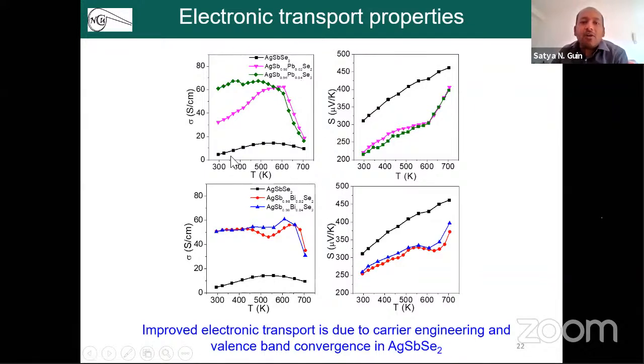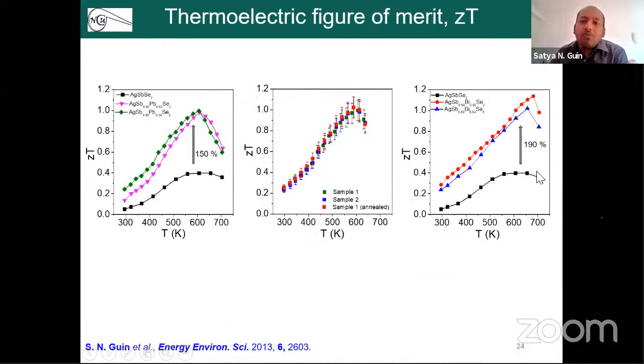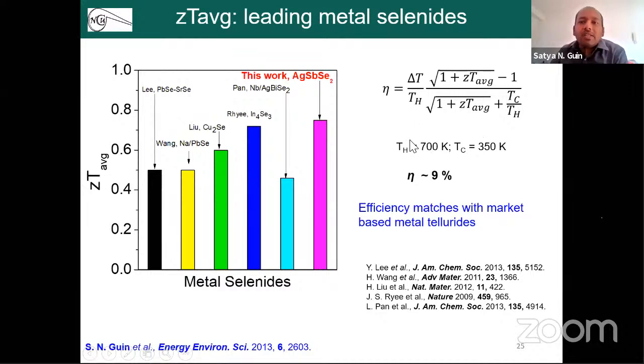And as a result of improved electrical and thermal transport, we have achieved an improvement of the thermoelectric figure of merit of approximately 190% in this metal selenide system, which is actually a record at that time. We further calculated the thermoelectric efficiency from the single leg, and we found this system shows an efficiency of approximately 9%, which matches with the market-based metal telluride system.